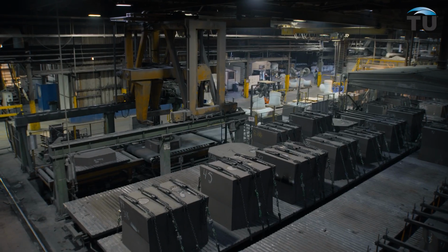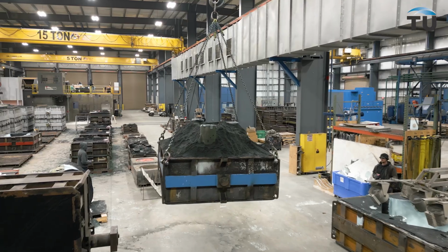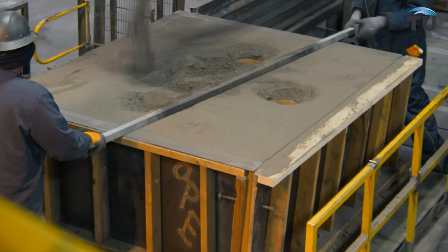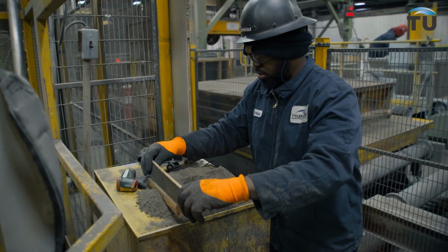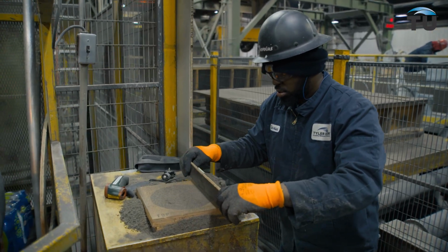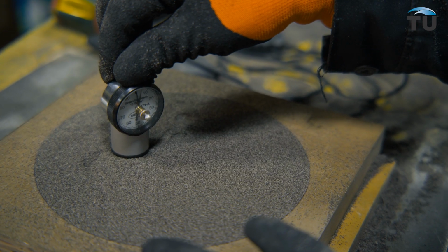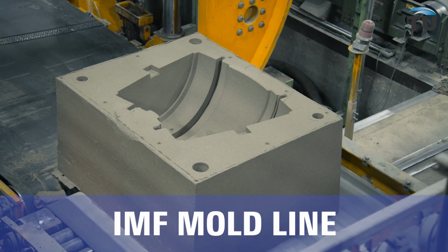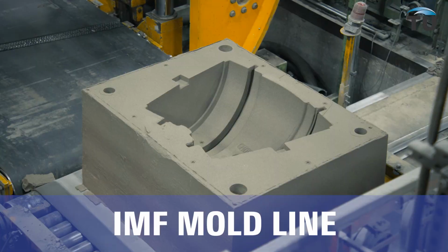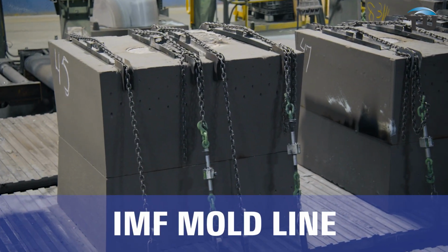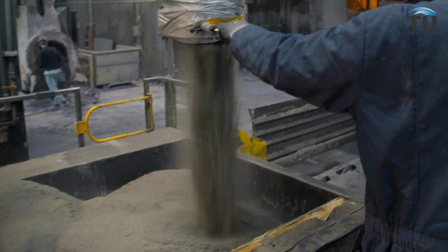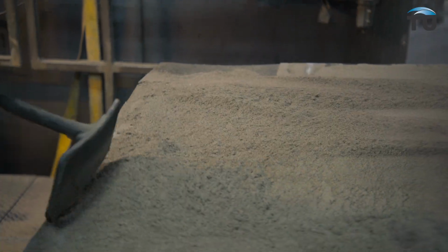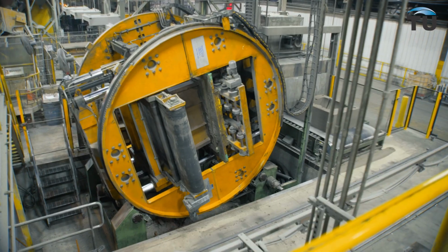The largest castings at Tyler Union are produced on 2 mold lines that use no-bake sand molding. This involves the use of a resin mixed with sand that starts to solidify upon exposure to air. The IMF molding line produces castings up to 48 inches in diameter. The process begins when a mold box is filled with resin-mixed sand. After filling, the box will set for 20 minutes before being rotated.